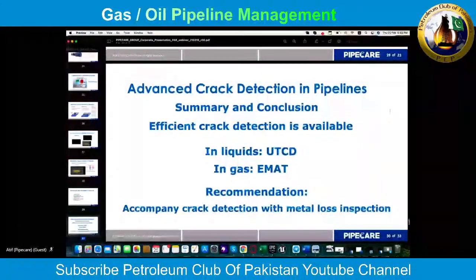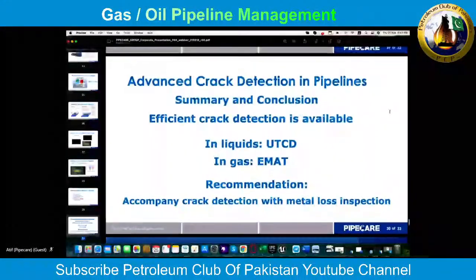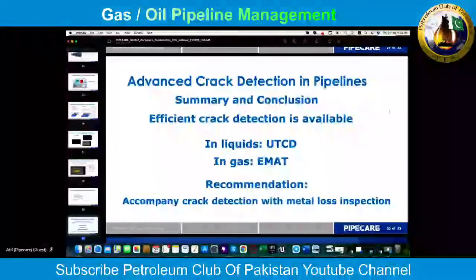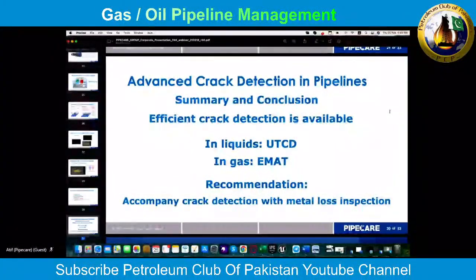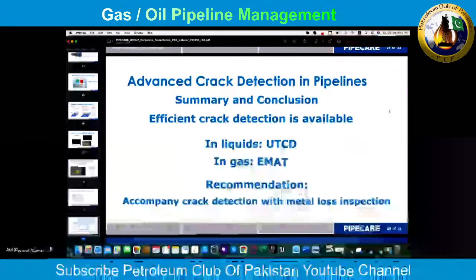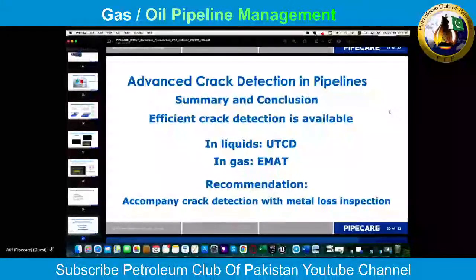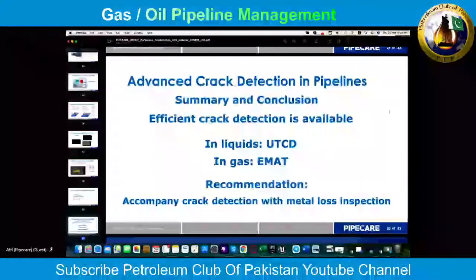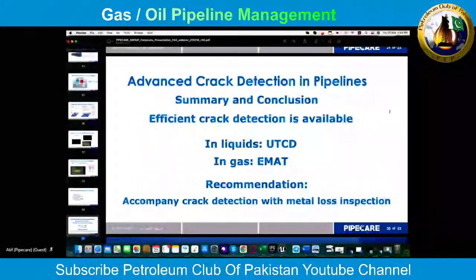Summary and conclusions. We have efficient crack detection methods available. For liquids, the best is the ultrasonic crack detection tool. For gas pipelines, definitely the EMAT tool. The EMAT tool can also work in liquid lines. However, I would always prefer the ultrasonic crack detection tool because it's easier to handle, it's lighter than the EMAT tool, and it's much easier to clean. The results of both tools are on the same level. This was one of the requirements when the EMAT tool was developed. It should be on the same confidence level as the ultrasonic crack detection tool.